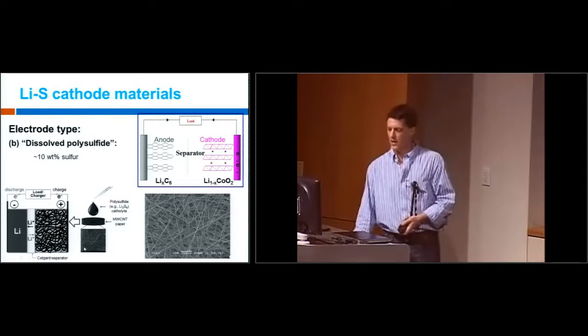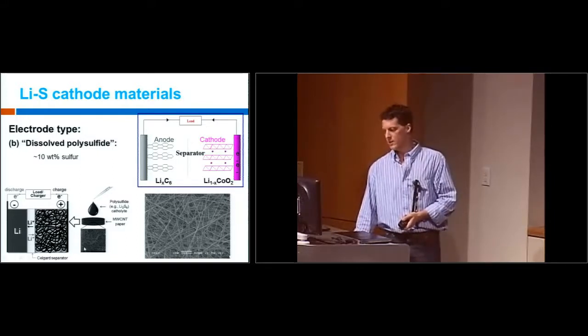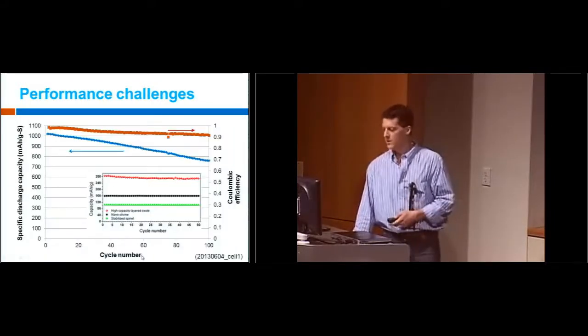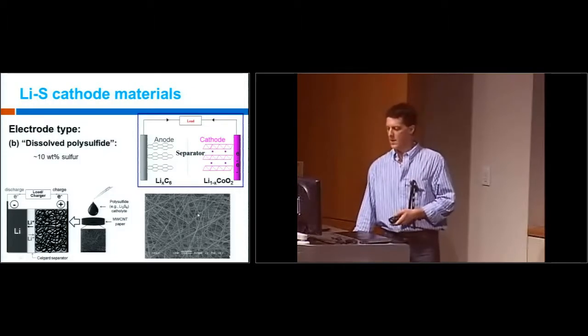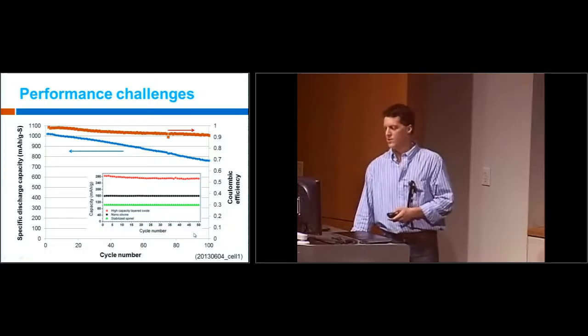For the dissolved polysulfide, as I said, you take a structured carbon. These are carbon fiber paper, and this serves as your cathode current collector, and then you seed the polysulfides into this layer. So this is not anywhere near as ordered as the other ones. And so you'll see also that there is quite a bit of capacity degradation in comparison. This is the state-of-the-art lithium-ion batteries, where you get pretty constant capacity.